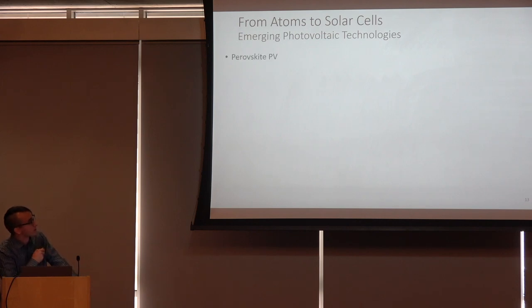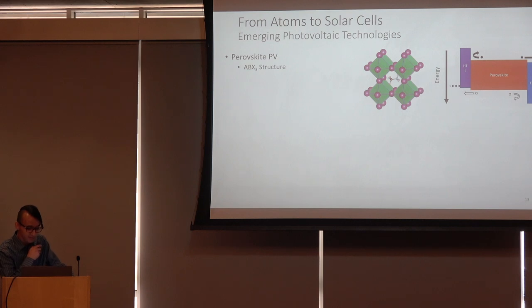And so, talking about these emerging photovoltaic technologies, perovskite cells are characterized by the inclusion of a perovskite material, which itself is characterized by an ABX3 crystal structure, as shown here. And in the case of a typical perovskite cell, you need at minimum three materials. You need your perovskite absorber, and then you need what's called a hole transport layer and an electron transport layer. And the purpose of these materials is just to provide that energetic landscape. Again, we're sorting charge, electrons to one side, holes to the other, and those two sandwiching materials provide that sorting. And then, of course, you need the external electrodes.